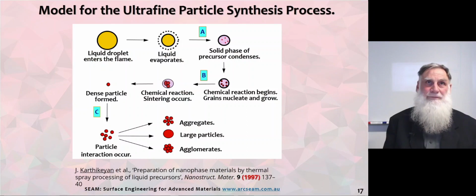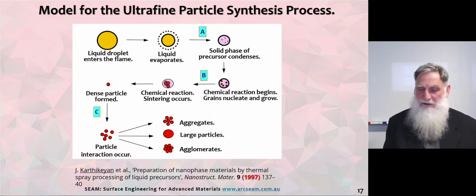In 1997. So the model for the ultrafine particle synthesis process is as follows. We have liquid droplets that enter the flame, the liquid evaporates, the solid phase of precursor condenses. This is the stage A. In stage B, chemical reaction can begin, grains can nucleate and grow because they're so small, they're nanostructured, recall. Chemical reaction occurs, sintering occurs, dense particles can form, and then in part C, these aggregates can be formed, large particles can be formed, or agglomerates. So the point now is that we're able to go from a liquid being injected into a flame to some result, some particles being formed that can then be deposited against the substrate.